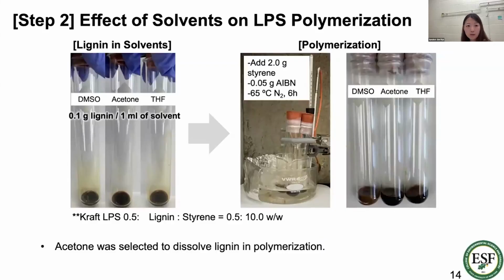Moving on to the next step, we can do the copolymerization using this modified lignin. But one of the challenges of using the modified lignin in the polymerization system is that it is hard to dissolve in styrene as a liquid. So we used different types of solvent to dissolve the modified lignin. We used three types of solvent: DMSO, acetone, and THF, and 0.1 gram of lignin was dissolved in 1 ml of each solvent. We added styrene and initiator, and radical polymerization was conducted at the given temperature in degrees Celsius.